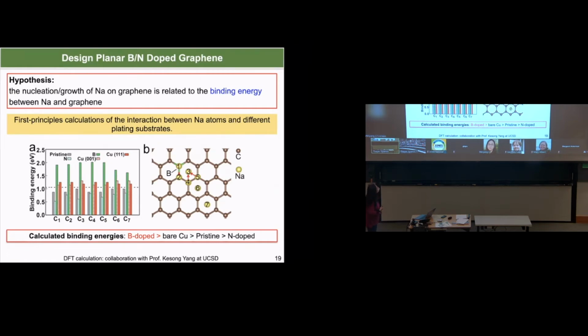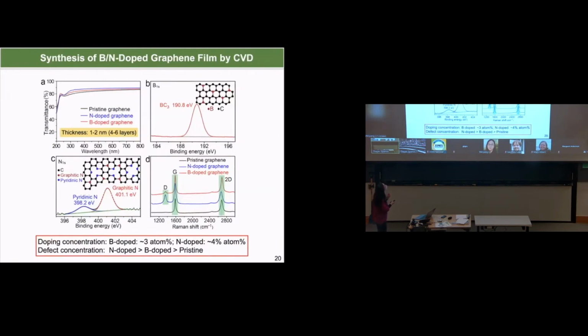You can see the calculated binding energy: boron doped graphene has the highest binding energy compared to a bare copper substrate and to pristine, meaning undoped, graphene, and it is also higher than nitrogen doped graphene. Experimentally, we achieved different doped surfaces of the graphene, including the ones we calculated, the boron doped and the nitrogen doped. This is the undoped, which we call the pristine graphene surface.